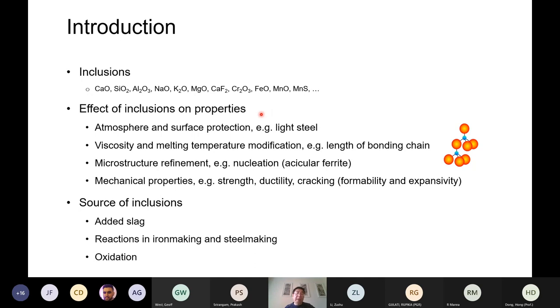So what are the effects of the inclusions? Firstly, we want those inclusions because steel making is at high temperature, 1000 to 1500 degrees. When the temperature is very high, the metal is very easy to get oxidized. In order to protect it and also reduce the heat loss, the best way to prevent oxidation is to use oxide. So people introduce a lot of oxide to cover the top of the liquid steel and protect the surface.